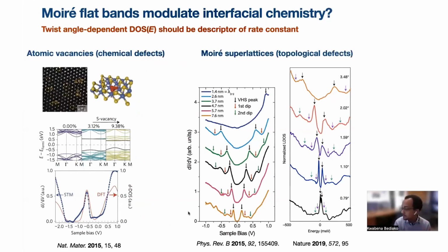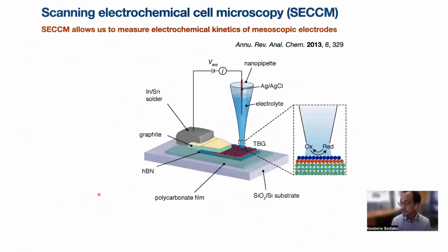Since this is a Park conference symposium, I think I should at least mention that we use our Park NX10 system, which allows us to do scanning electrochemical cell microscopy experiments. So we take a nanopipette and fill it with electrolyte. The electrolyte protrudes a little bit from the base of that nanopipette. We can touch down onto our sample, and we can do electrochemistry within that little meniscus using this system.